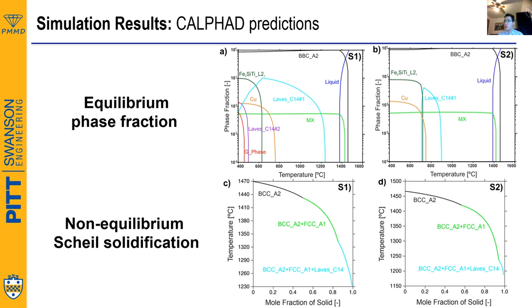The only difference between the two samples regarding L21 we see is just the temperature window upon which the L21 is expected to exist. In the case of S1, the temperature window is much smaller than in the case of S2, and that's because S2 has a higher content of titanium and silicon.